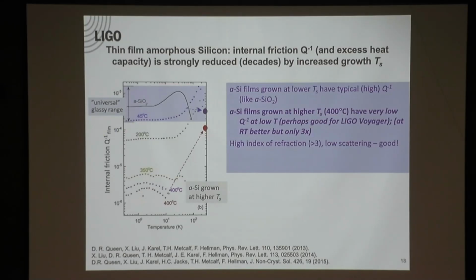The remarkable thing is what happens when I grow it at elevated temperatures. When I grow it instead at 400 centigrade, which is just before it starts to crystallize, it is unequivocally not crystalline, not nanocrystalline, not precursors. The loss is way down here, orders of magnitude below the universal range. That's the thing that caught everybody's eye, because everybody's been trying to find a material with low losses. I can make amorphous silicon, high index of refraction, really low losses, not quite as good at room temperature, which is what we care about, but even room temperature is a lot better than anything else that anybody's making. We've recently found a way of beating the absorption down quite a bit by using hydrogen during our growth, so even that we're making some progress on.